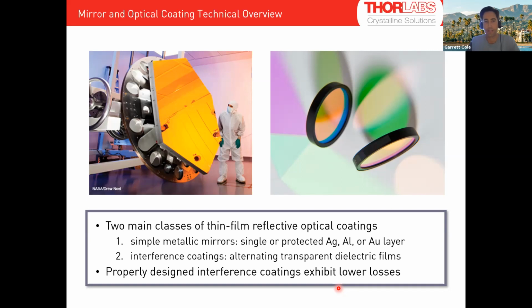So you're not going to make a high finesse cavity out of this. And due to some of those facts, like the intrinsic absorption, your laser damage threshold is going to be somewhat limited. So if your aim is to make a high reflectivity mirror beyond what you can achieve with a metal, then you're going to switch to a dielectric structure. And really the basic fundamental difference is the fact that the constituent materials that make up that mirror are transparent, right? Whereas the metal is absorbing and is reflecting based on the fact that you have these electronic interactions. Here you're relying solely on Fresnel reflections in a transparent medium. So if you use a properly designed interference coating, you're going to get lower losses just given the fact that it's non-absorbing. And if it has a nice sharp interface and smooth surface, you can reduce the scatter.